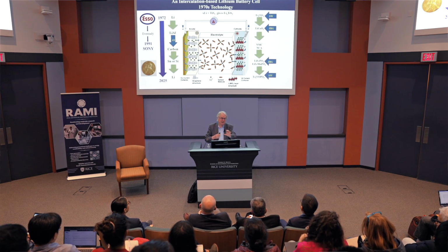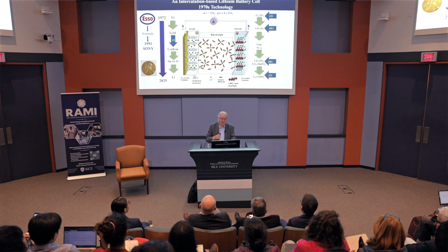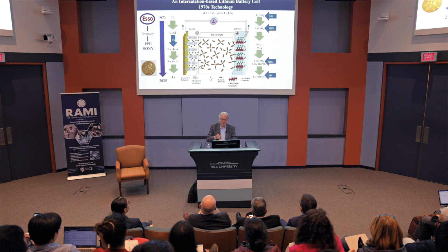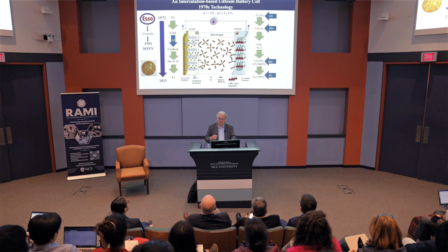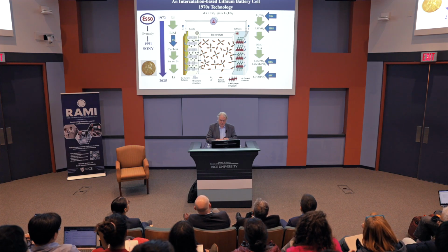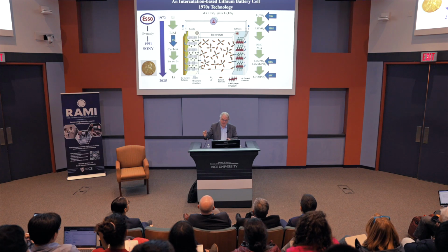I'll come back to that material because that's now a hot item, because in America we got lithium, we got iron, we got phosphorus, and clearly we got oxygen. So we got all the minerals we need there. We don't have the nickel and cobalt in the US. So from lithium iron phosphate, it's now interested in lithium manganese phosphate.